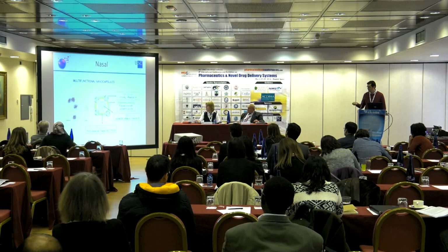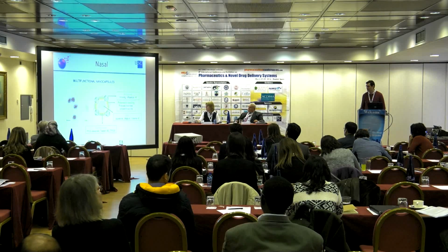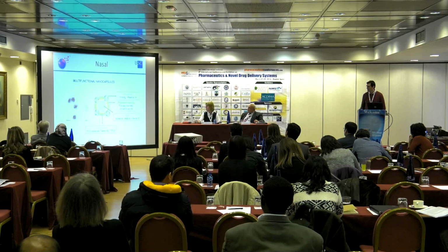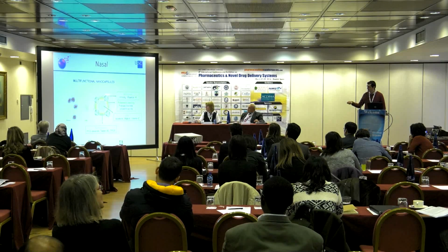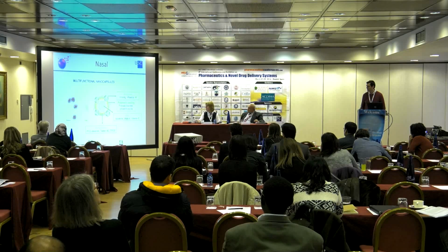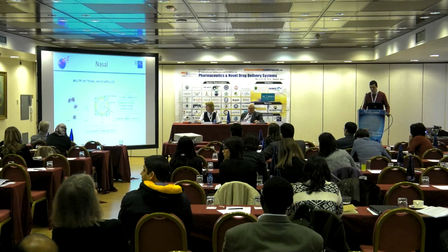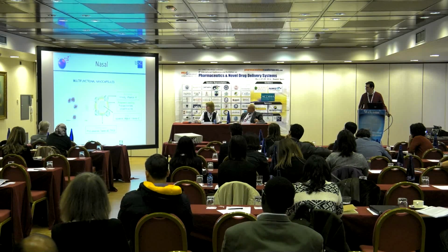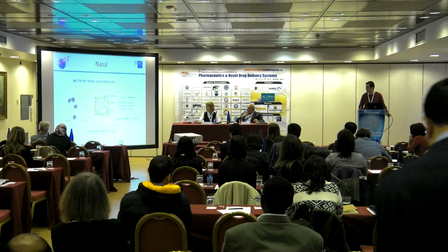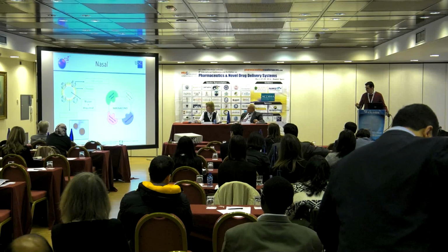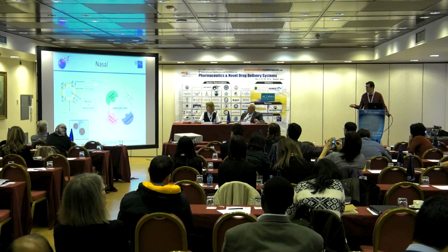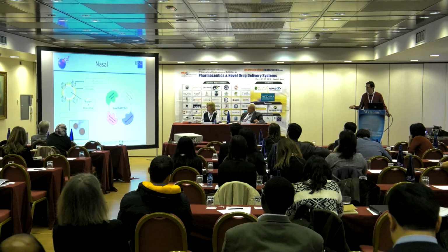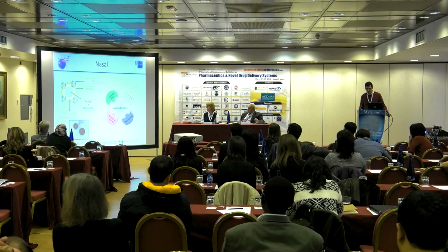They have an oily core. We can put here immunostimulant oils like squalene or vitamin E. We have different surfactants stabilizing this oil, and then it's important this polymeric shell, where we can have different polysaccharides or polyamino acids. And we used as reference antigens hepatitis B antigen and influenza antigen. So I'm going to show now some results with hepatitis B antigen and chitosan nanocapsules that contain in the nucleus imiquimod, that is a toll-like receptor agonist.